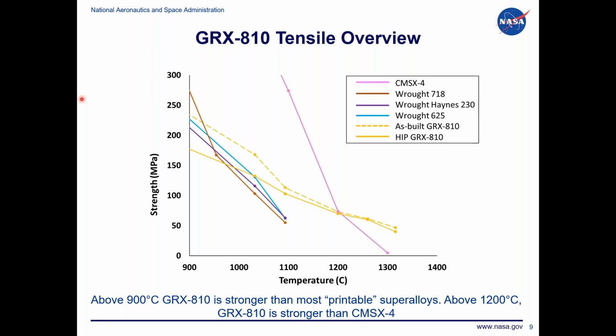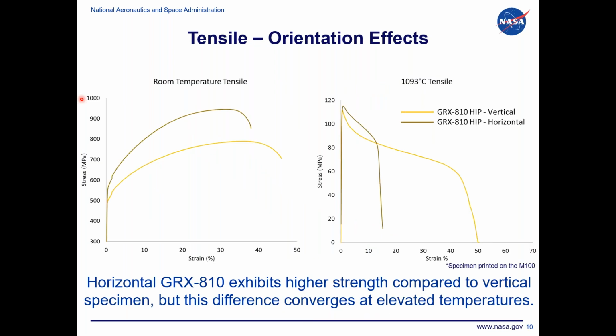And by the time you hit 1300 C, I was even surprised by this. There actually is some tensile strength left in this alloy, and we're talking 98, 99% of its melting temperature, which is really, I think, remarkable. And we've done other studies at these temperatures, and I'll show that. But I'm more and more convinced that this is real.